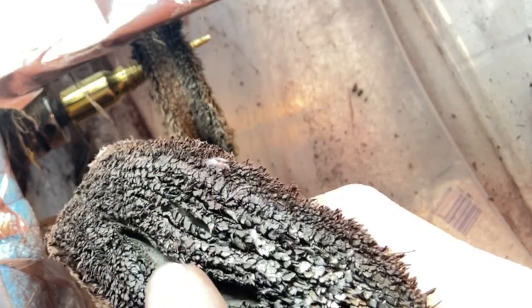Now with the polishing wheel, they're very prone to getting some buildup on them. And that will look like this. This is an extreme example, but the ends of the fabric get flocked over with compound that's built up in a residue. So the first stage, usually of using any polishing tool, is to fluff it up. And I'm always repurposing things to use for this. I've made my own, like this one. This one is a pet grooming brush.